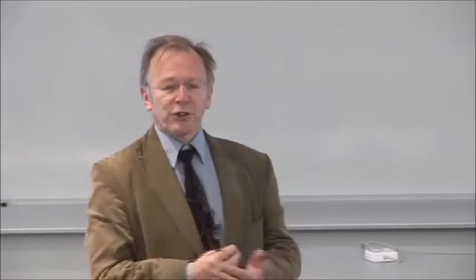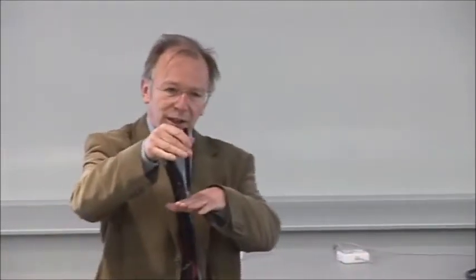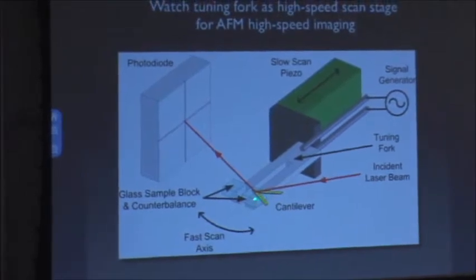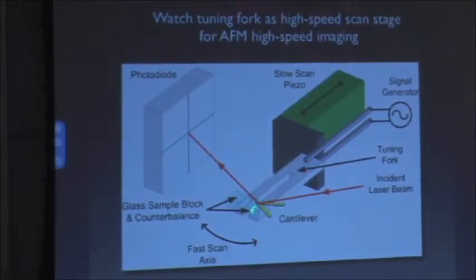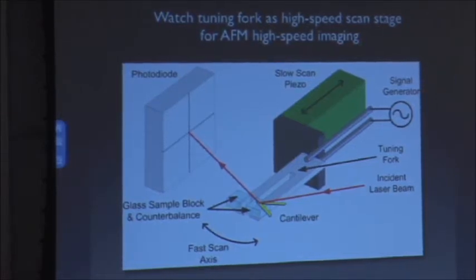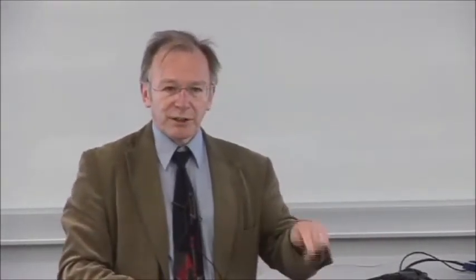And then I said one day, why don't we just try doing AFM? This was a stupid idea. So we took our tuning fork that was driving our optical fiber, and we turned it on its side, and we put a sample on it. In fact, we put 2 little glass blocks. These are only a millimeter square. This is a watch tuning fork. It runs at 2 to the 15 hertz. It runs at about 30 kilohertz when you've got some mass on the end. And we used an ordinary AFM cantilever, and we did the usual beam deflection to measure the bending of the cantilever. And we imaged a polymer sample. We clearly knew that the sample was going to be destroyed by doing this, putting a sharp probe with a high force, 100 times higher force than normal, in order to accelerate over the bumps. Scanning it at 30,000 lines per second compared to 1.